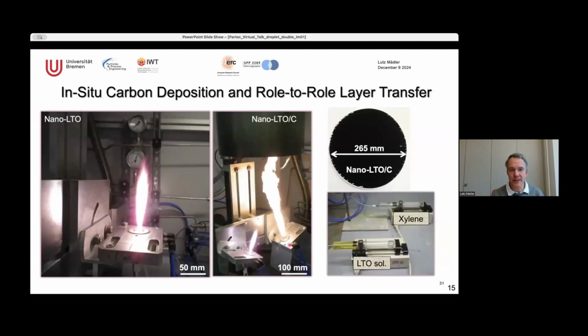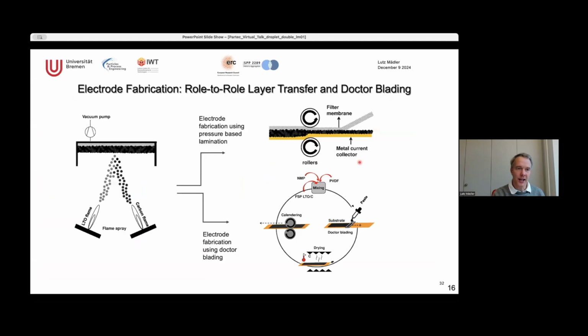So this is a carbon flame. It's an exaggerated picture, but it makes the point. I think we can basically make the carbon and the actual lithium titanate together, and we mix it. We collect it on that filter, and then we can use that powder directly as a lithium titanate carbon mixture. And schematically, how we do this is shown here. We have these two flames, the carbon flame and the anode material flame, and we collect them on the filter.